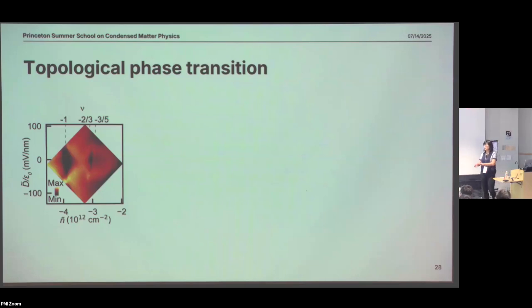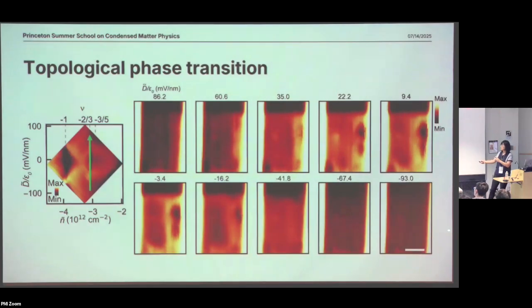Here, the advantage of working with this material is that the displacement field is a nice tuning knob. So if we follow this green arrow, we fix the filling at nu equals -2/3 and drive the displacement field from very negative to zero to very positive. What we saw is that it is homogeneously dark, meaning insulating, and also insulating on the other side. In the middle, only in the topological phase, you can see the edge being conductive and the bulk being insulating. This confirms that we did see a topological phase transition, and the edge state is not always there.